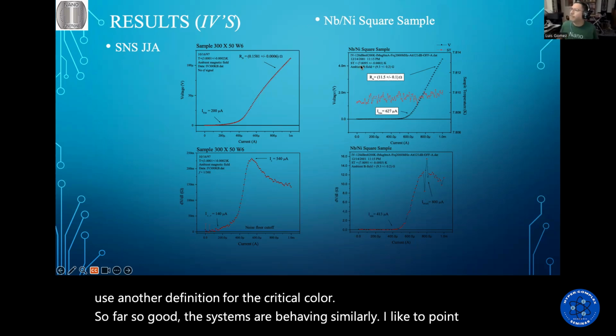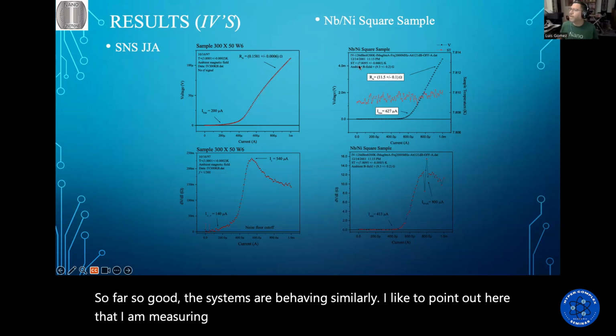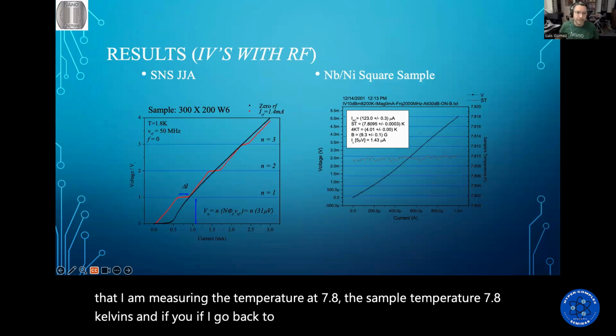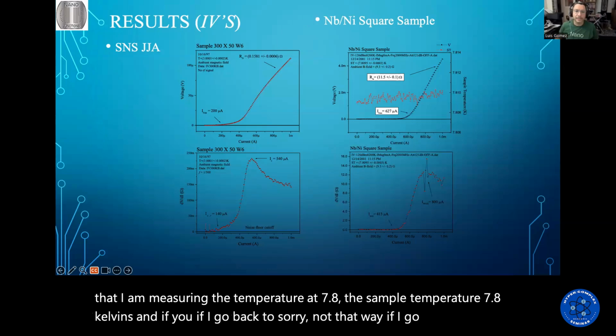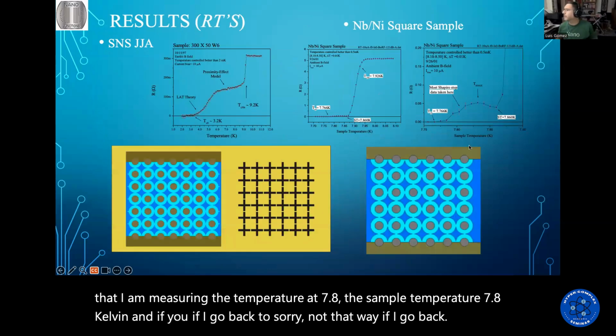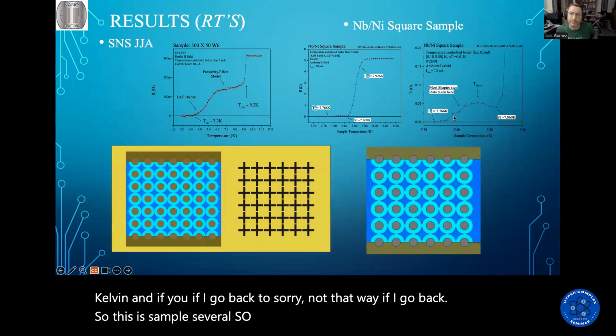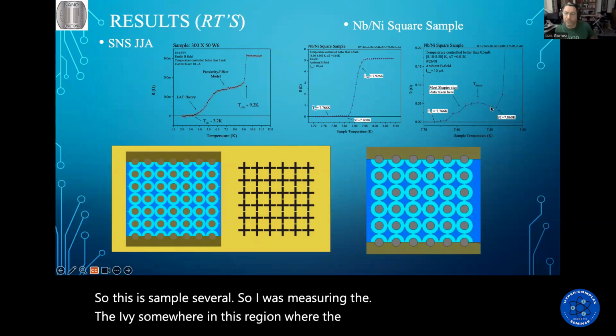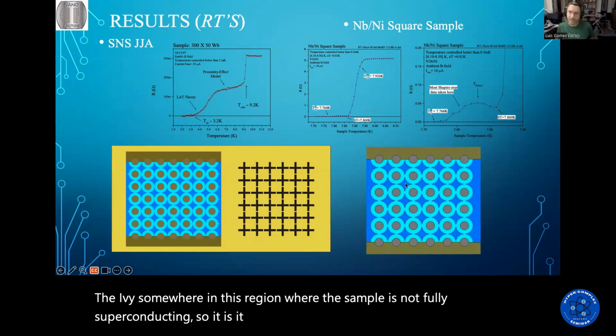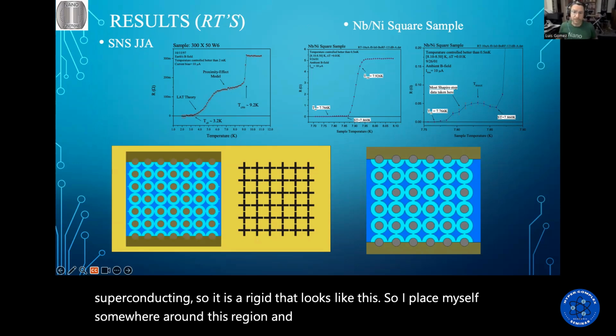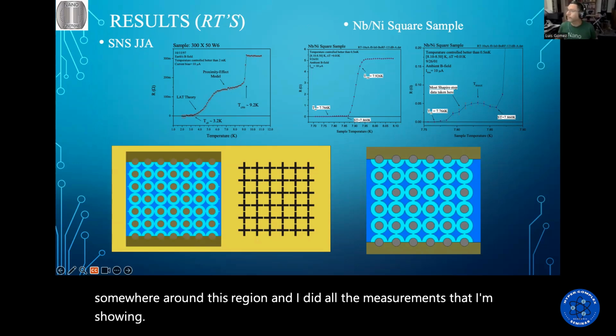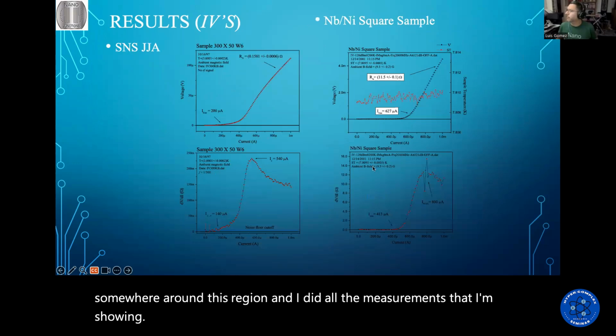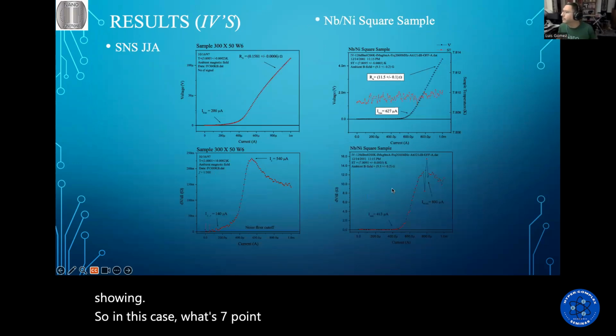I'd like to point out here that I am measuring the sample temperature at 7.8 kelvins. If I go back, this is sample temperature - so I was measuring the IV somewhere in this region where the sample is not fully superconducting, in a region that looks like this. I placed myself around this region and did all the measurements I'm showing you, so in this case it was 7.8 kelvins.